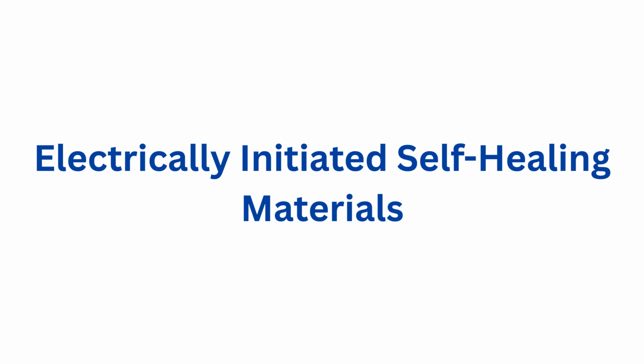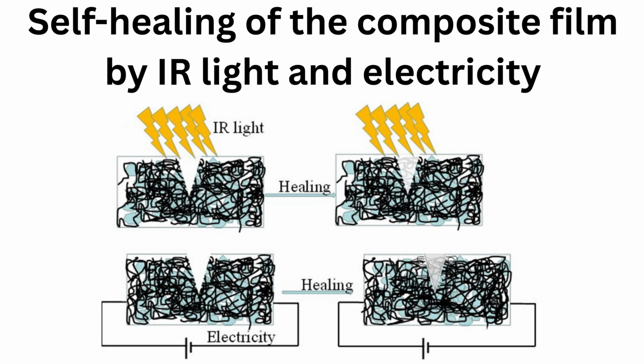Electrically initiated self-healing materials. Electrically triggered self-healing materials refer to the self-healing effect achieved by using the Joule heat generated by an electric current to drive the dynamic bonding within the material to undergo reorganization. Scientists prepared a graphene thermoplastic polyurethane (GTPU) flexible conductive film using a blending method, which can stimulate the healing of the film by electrical and infrared light triggering.